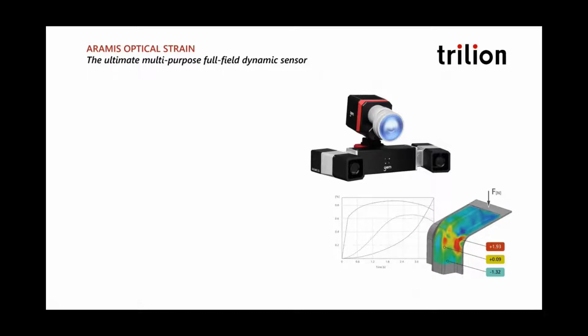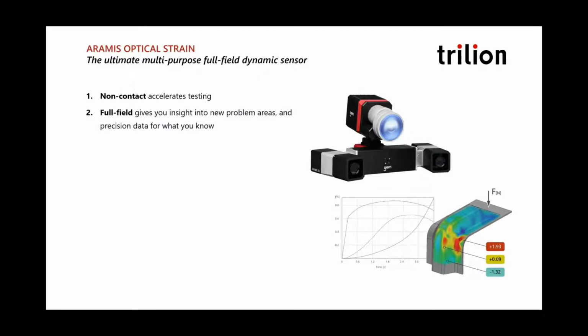So the system is very powerful in the sense that not only are we measuring full field, we can bring the CAD model in, so all the data is going to be in your true CAD coordinates. We can get the results and see full field the results that are happening. You can put your gauges down after you already know the results, and so you can really interrogate the results and get the data that you want for your measurements. It's a non-contact measurement, so it's fast and efficient to set up and measure.